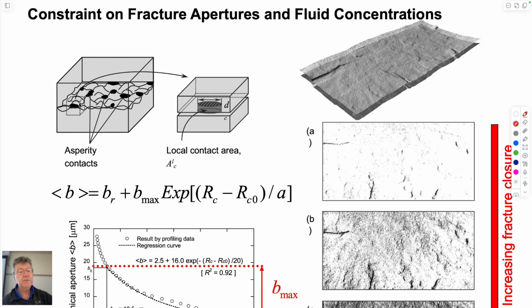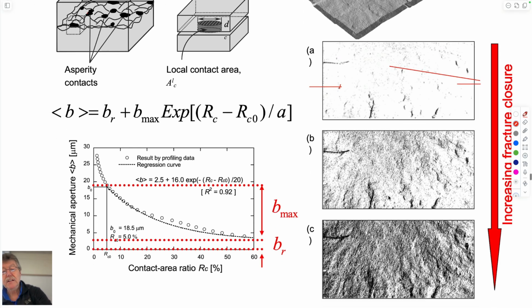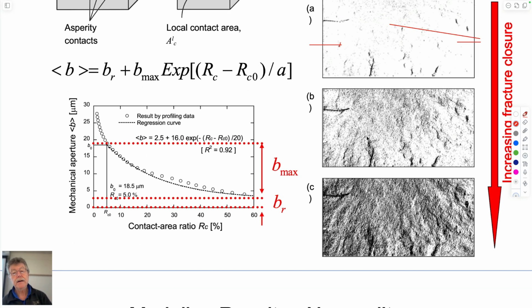Here you can represent the individual asperity contacts as these individual grains, and you can look at the growth of them. You can model the fractures as two halves. You can look at flow within these two halves from upstream to downstream. And you can just look at a mass balance of water being carried within the fracture, dissolving material from around these asperities in the free face, having mass ejected into the water by pressure solution from mass balance and being transported downstream, and then being able to precipitate, and then look at the growth in the contact area of the fracture. Contact area is shown dark here, growing as a function of time.